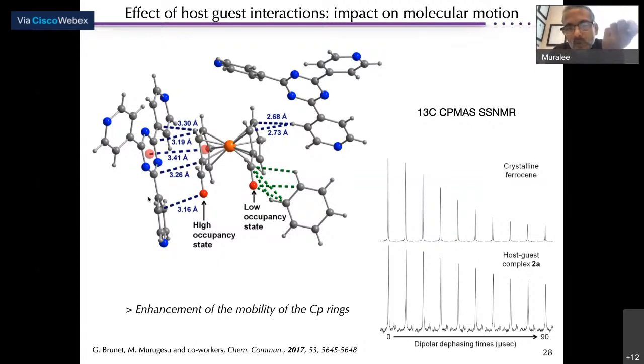So what we wanted to know, once the molecule is inside, is it stabilizing? Is the structure more retained in terms of the Cp? Is it rotating? What we wanted to find out through solid state NMR, through the dipolar dephasing technique, we were able to probe the crystalline ferrocene and the guest ferrocene within the framework. The dipolar dephasing time changes drastically. You can see the decrease here, while this is much longer in terms of dipolar dephasing times, which leads to the conclusion that within the framework, the ferrocene molecules rotate much faster than when they are in a crystalline state.